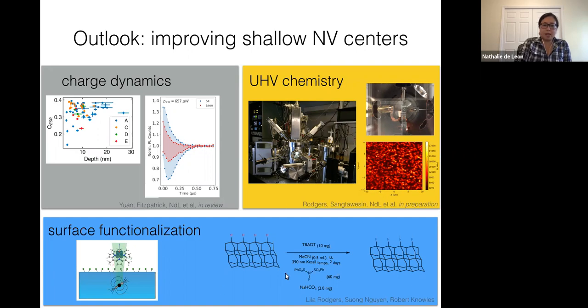And then in parallel, what we've decided to do is start revisiting this question of whether or not it's possible to do normal conventional wet chemistry at the diamond surface. Normally, this is quite hard to do because diamond is inert and it has this really tight lattice constant. So doing conventional wet chemistry with high yield is generally thought to be impossible. But what we discovered is that there's this brand new class of catalysts that have been developed by the synthetic organic community over the last decade or so called photoredox catalysts, where you get very different catalytic behavior just by shining blue LEDs on your catalyst.